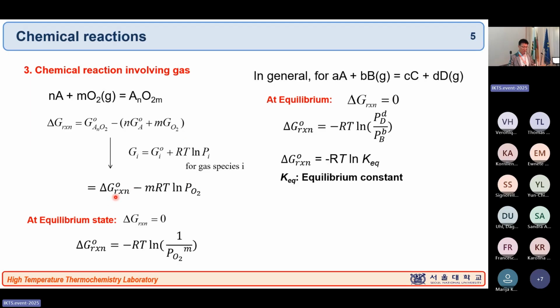So if you consider this one in this equation, you can sum up and summarize this equation in this way, which now contains the partial pressure of oxygen. Now we have an interesting game. Previously, when I said everything is pure, a solid becomes another solid, then nature just decides your Gibbs energy. So we cannot do anything. Either it goes forward or backward, or in equilibrium state, both together.